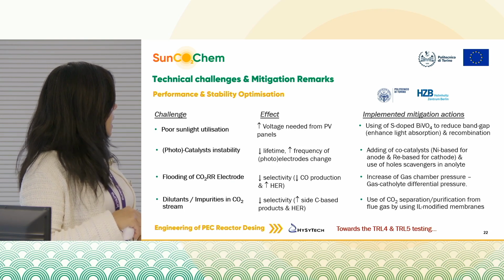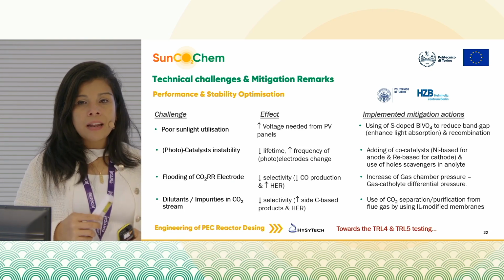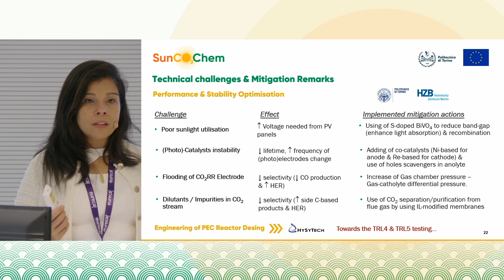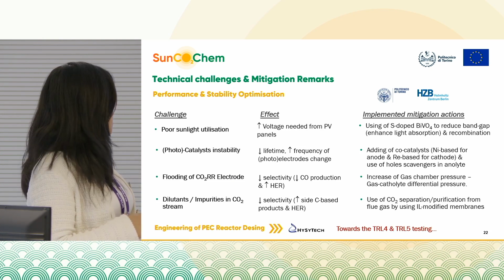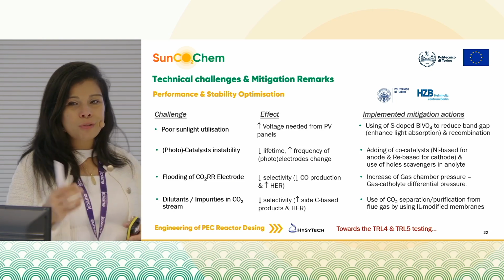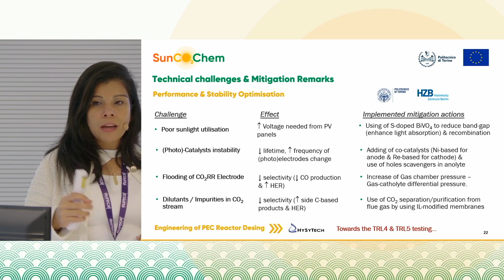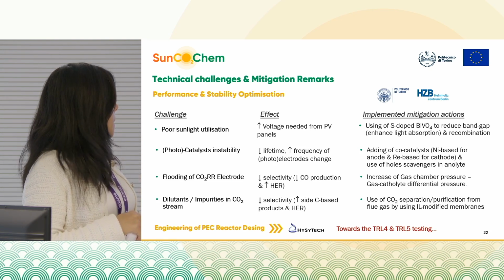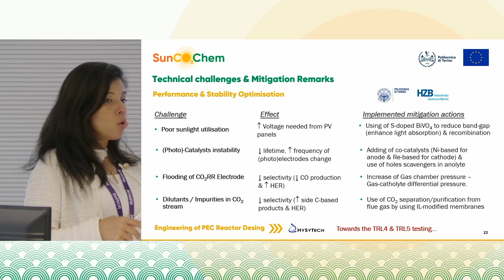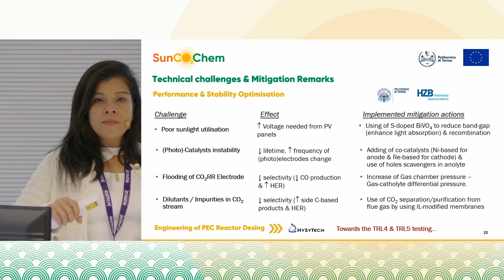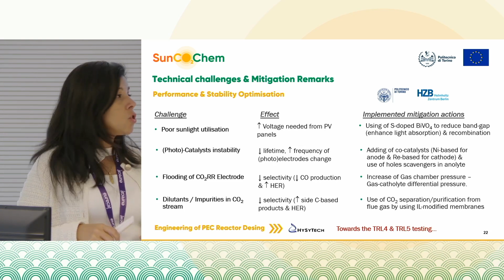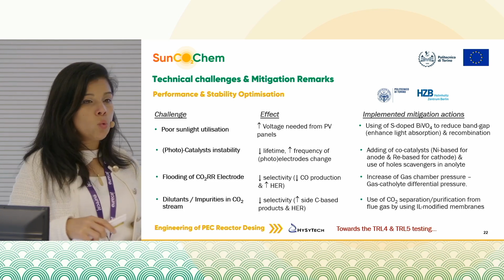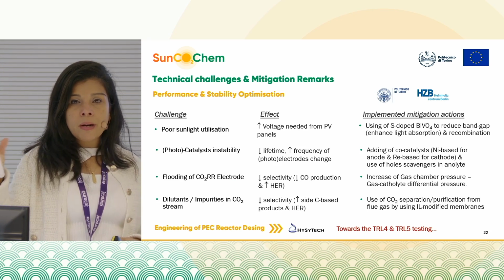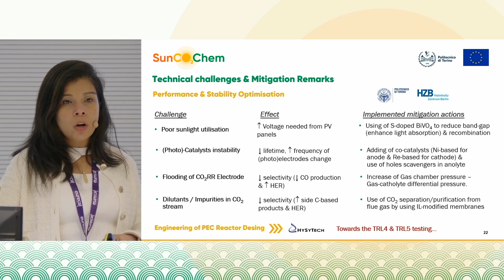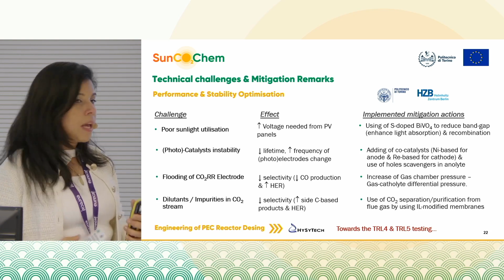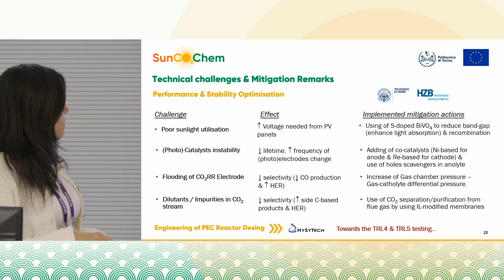Regarding the flooding of the electrode, as I just mentioned, this can hinder the selectivity of the process and the CO2 reduction, and actually is one of the problems that we had also during the TRL4 demonstration here in EURECAT. But this can be solved actually, and was solved in the TRL5 prototype, by being able to regulate the pressure in the gas chamber. In that way, we are able to control the differential pressure between the gas chamber and the electrolyte, and in that way be able to recover the CO2 reduction ability.